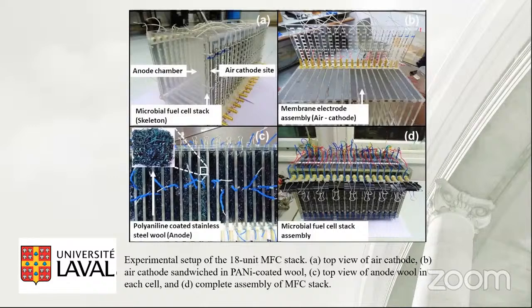After developing several small reactors, we constructed an 18-unit microbial fuel cell stack for power generation as well as landfill leachate treatment. We realized very good performance. Our idea was to develop something that can give 12 volts, because 12 volts is a typical battery application. We consider this a bio battery for low energy consuming, small electrical instruments. That's why 18 cells were considered, because one microbial fuel cell can give around 700 to 800 millivolts as open circuit potential.